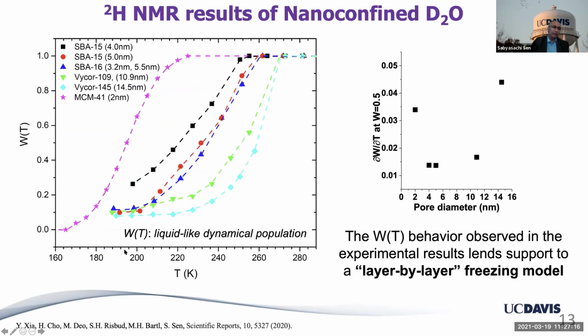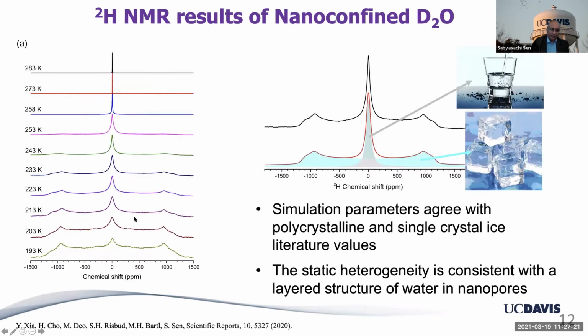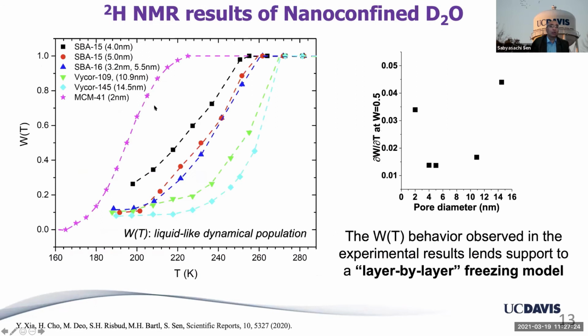This becomes more apparent if we plot the liquid-like population, basically the area of this narrow peak divided by the total area of the signal. And here you can see that, and this data point is from literature done in MCM41, which is the smallest of the pore. But here you can see that, as you lower the size, the appearance of the drop of the liquid-like population moves to lower and lower temperature,